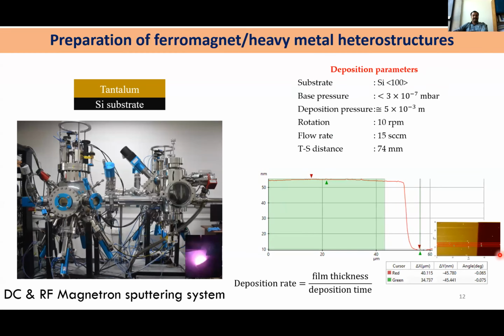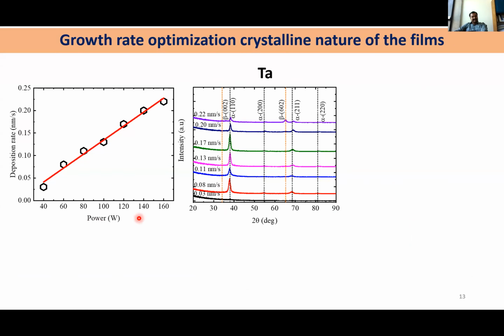You can see that by creating a step, we could measure the thickness to optimize the growth rates, right? So what we have done is that by increasing the DC power, we have changed the deposition rates by keeping all other parameters constant, like rotation rate, background pressure, and argon flow rate. Interestingly, when we increase the growth rate of the tantalum to 0.17 nanometer per second, we get a pure alpha phase, and above which, from 0.2 to 0.22 nanometer per second, we are seeing a mixed phase, that is, beta phase is getting nucleated.